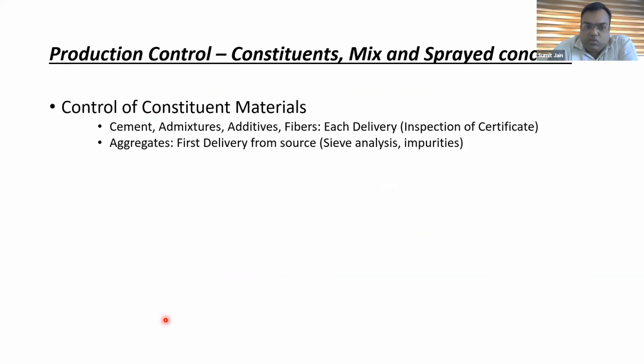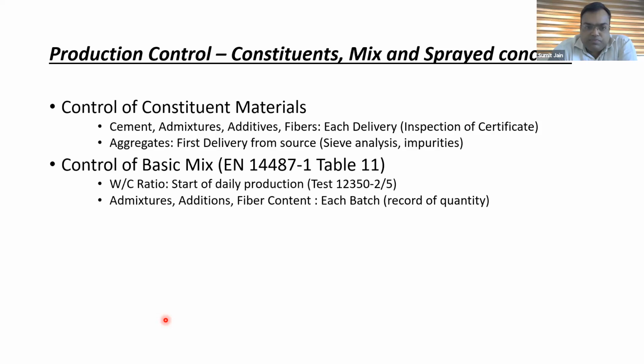When we come to the constituent materials, we have to qualify cement, admixture, additives, and fibers. As per the standard, inspection category 3 of the European norm, each delivery of these constituent materials has to be checked from the inspection certificates. For aggregates, the first delivery from the source has to be checked, which includes sieve analysis and other tests like impurities and alkali aggregate reactions.